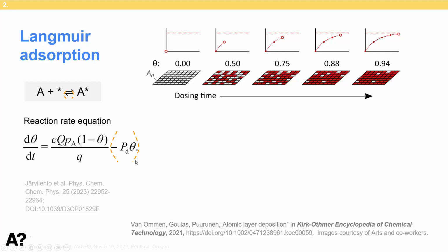That then depends on the surface coverage, but often this one is forgotten, neglected, or not allowed in ALD studies. So only the forward reaction is allowed, meaning that you have irreversible reactions. Reversible reactions are not taken into account because they don't fall into the definition of ALD. To simplify things, this is how it's often done.